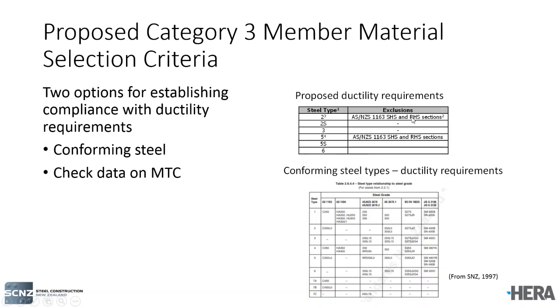The reason that we have excluded them from the conforming steel type is that if you go to the product standard for 1163, for SHS and RHS sections, the minimum elongation at fracture value is only 12%, which is lower than the 15%. If you want to use an SHS or RHS section, that's not a problem. There's an alternative path that you can follow. You can also demonstrate compliance with the ductility requirements by getting a test certificate and comparing them against the requirements that we're proposing. So there is a separate pathway for such elements or such product types.